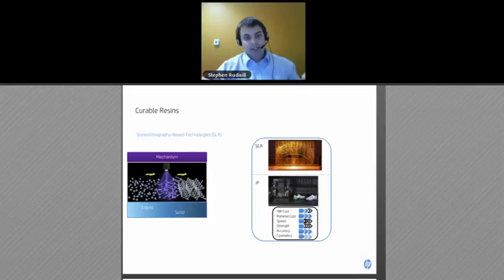And essentially the advantage of these technologies is mostly accuracy in your Z dimension. So fused filament fabrication, or FDM, fused deposition modeling, the hot glue gun plus the robot technology, has a problem with controlling the size of the glob you get. There's kind of a sweet spot to be in where you don't get too much overmelt or too much extra material coming out, versus the speed of the robot, and those things have to be optimized. And so you're kind of limited in your Z-dimensional accuracy.